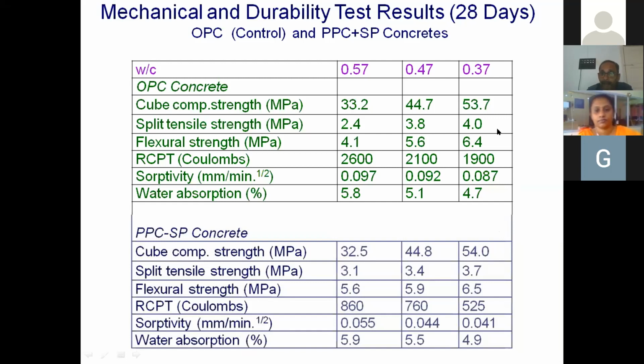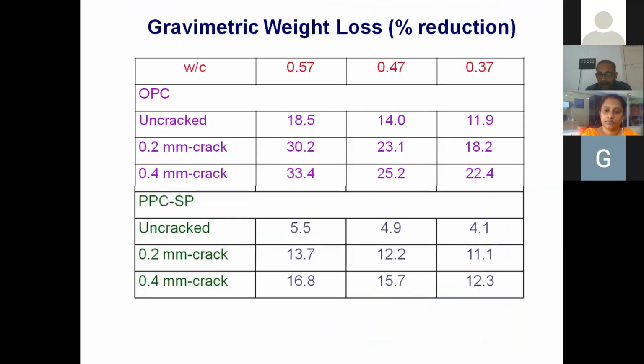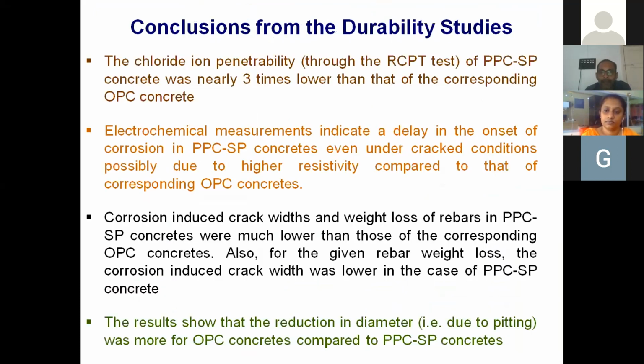Tensile strength and splitting tensile strength are a little higher. But look at the RCPT value and sorptivity value. The values are much reduced for the cements with a fly ash. That means the durability of the concrete is much higher with the blended cements, just like gravimetric loss and all those things.